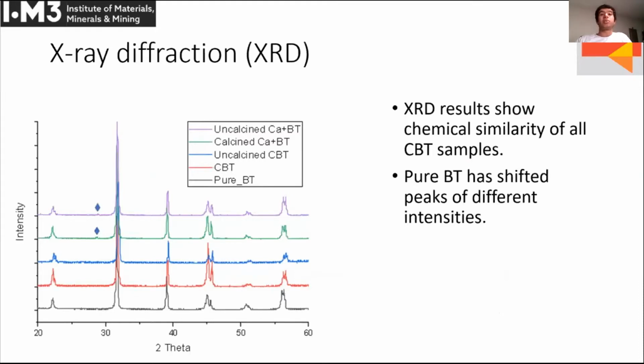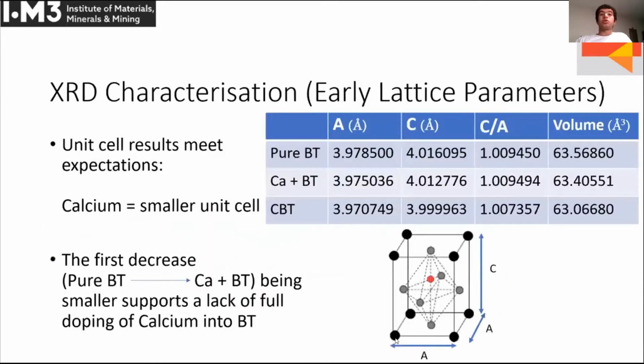With XRD as well, you can characterize these distances of the unit cell. As discussed, calcium is a smaller atom, so we expect the unit cell would be smaller. We can see pure barium titanate has the biggest lattice parameters, and as you add calcium to preformed barium titanate, that shrinks down, and when you put calcium barium titanate together, that shrinks down even further.